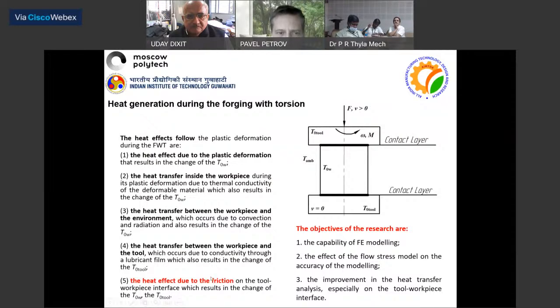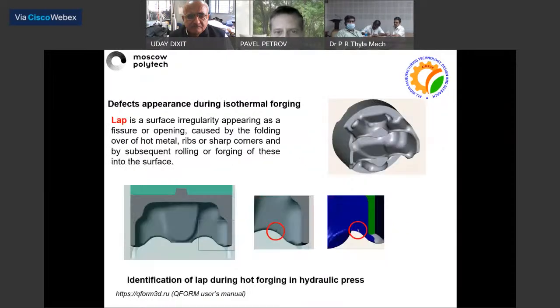The model took into account several heat effects, and much more important for the forging with torsion is that the driver of this process is linked not only to a heat effect due to plastic deformation, but also the heat release during the shear deformation within the very thin contact layer. As will be seen further, the heat effect during the shear deformation within the working stroke of forging with torsion is 2 or 3 times more than the heat effect due to plastic deformation.